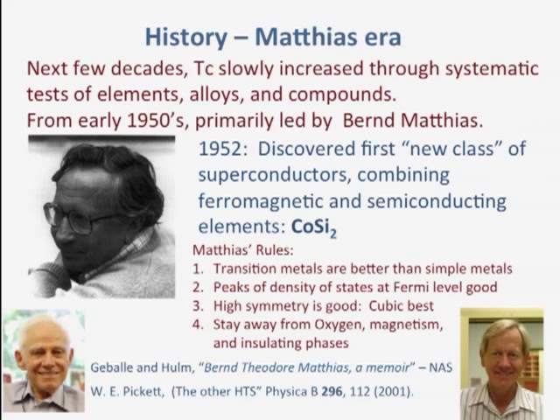And he had these rules here. Transition metals are better than simple metals. That still holds for the high TC. Peaks in density of states at the Fermi level are good. And in another colloquium, I go into showing how accurate this is, that you want a large density of electronic states near the Fermi level, and that helps superconductivity. That's the McMillan equation, and holds in huge numbers of materials. So these things still hold.